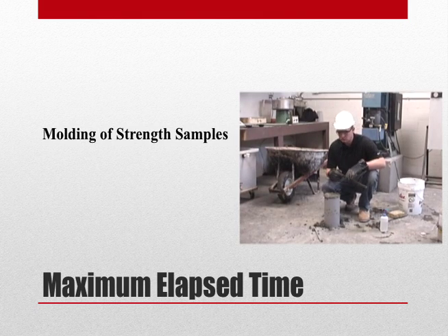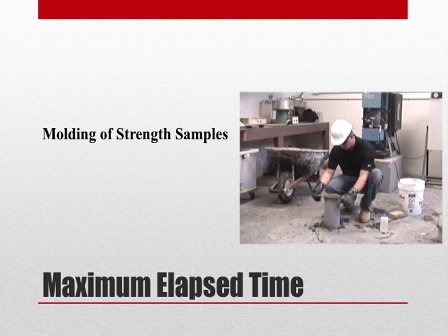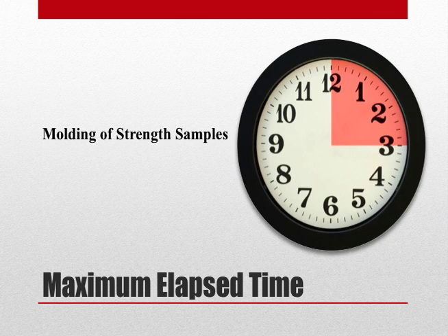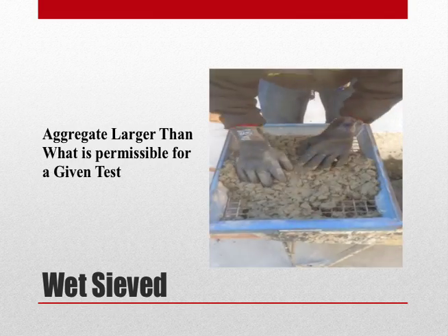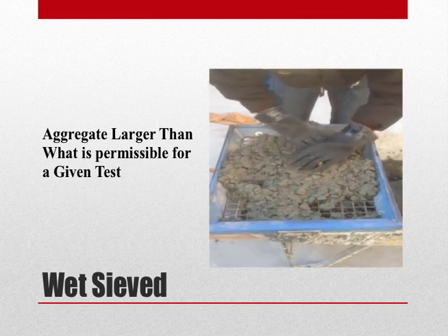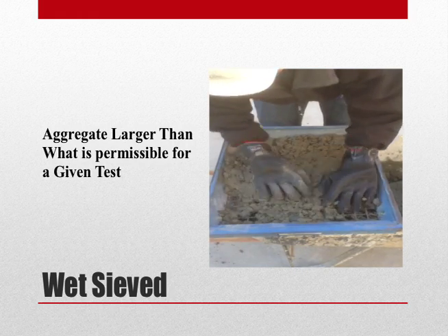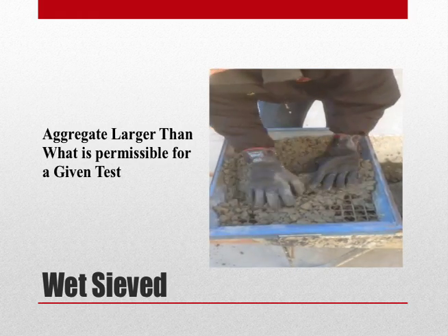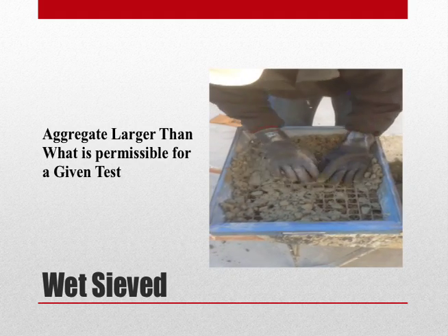However, the maximum allowable time between obtaining our sample and fabricating test samples is also 15 minutes. Lastly, whenever there is aggregate larger than what is permissible for a given test, the sample must be wet sieved over the appropriate size sieve.